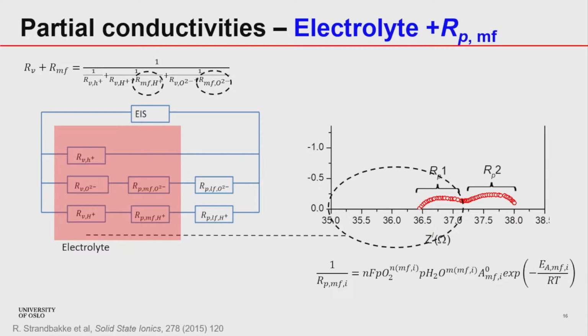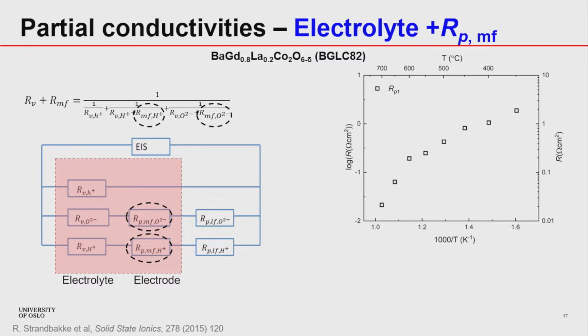Also, we can relate these parameters with the rate equation, where we have the dependencies on the PO2, PH2O, pre-exponential factors, and activation energy. And by doing that, we can have proper fits of the log R versus temperature. Here we can easily see two activation energies related to proton, positive effect of proton conduction at low temperature, and this is related to oxide ion conductivity, and also a bit of p-type conductivity at high temperatures.